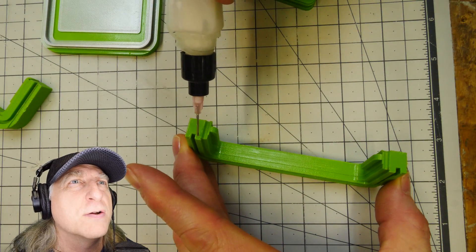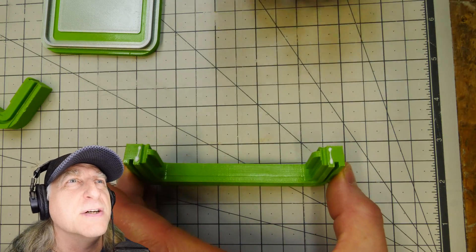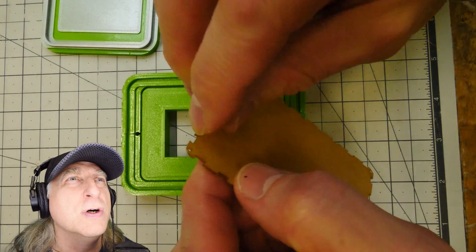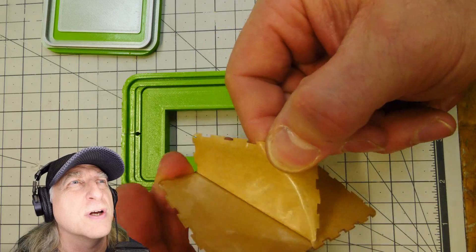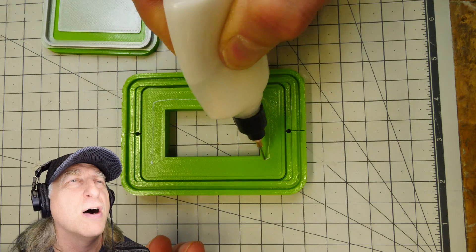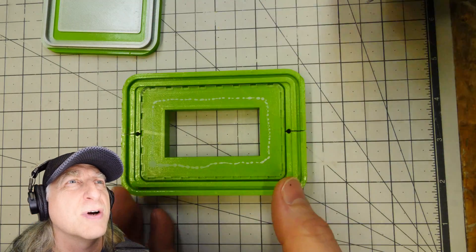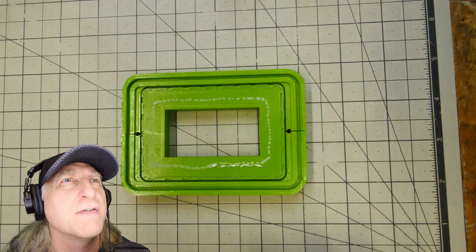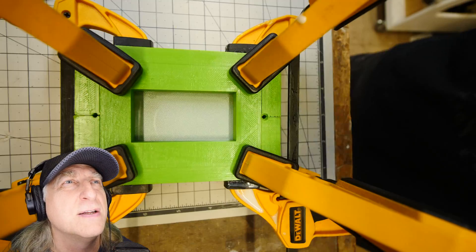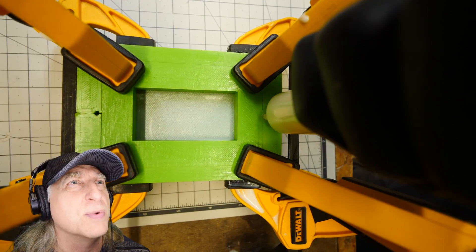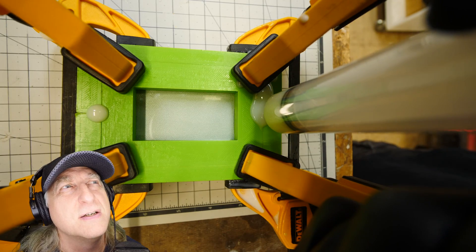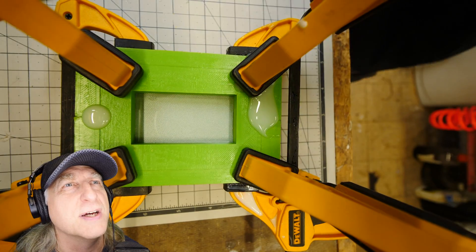I'll just use a little bit of white glue, some PVA. This will help me seal a few places in the mold but it'll also allow me to basically glue the clear acrylic in place and keep it from moving. I place the PVA on the mold, not on the lens so I don't scratch it. I do the other half and I snap the mold together. Once that's dry, that will lock the clear acrylic in place and prevent it from moving around during the injection process.